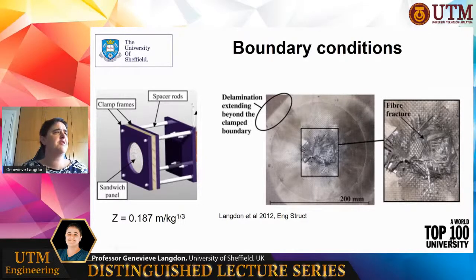So in this set of experiments, and maybe this is a good time to illustrate how we do these tests, we would typically clamp the specimen inside a clamp frame, which is shown on the far left of the image. You can see a purple clamp frame and a white panel inside it. And then that is typically attached to something. In this particular experiment, it's attached to a ballistic pendulum.